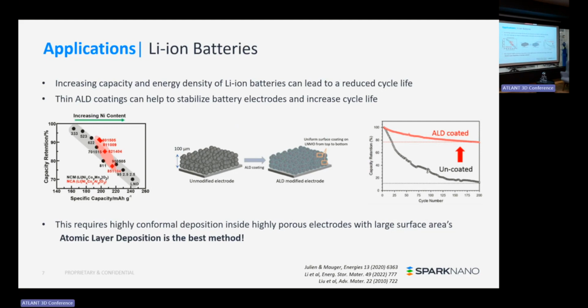Yesterday we had a very nice talk by Alex, where he already explained a few of these things. One of the issues, for example, if you want to increase capacity and energy density of lithium-ion batteries, is that you can use different electrode materials, but reactivity comes back to bite you, so the cycle lifetime of the batteries can be reduced. Very thin ALD coatings, maybe even a few cycles, can help to stabilize these battery electrodes. Again, this requires highly conformal deposition inside highly porous electrodes with very large surface areas. And again, ALD is, of course, one of the best methods to do that.